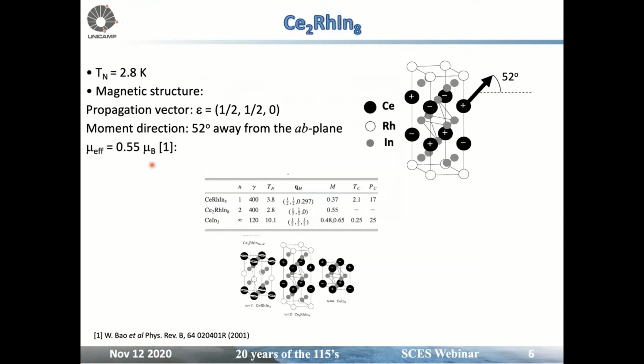So Ce2RhIn8 was studied and had its magnetic structure determined by Bao, and he found a magnetic structure with propagation vector (1/2, 1/2, 0) and moment direction 52 degrees away from the ab plane, and an effective magnetic moment of 0.55 Bohr magnetons. So that's the Ce2RhIn8 magnetic structure, and that's comparing with